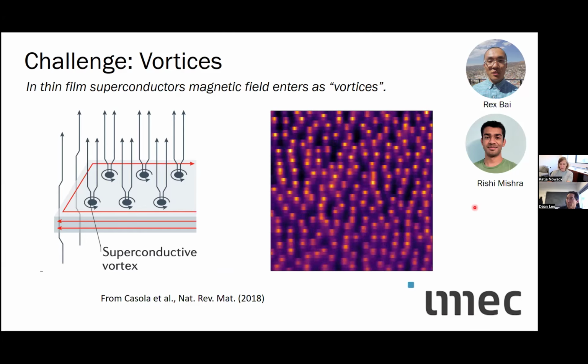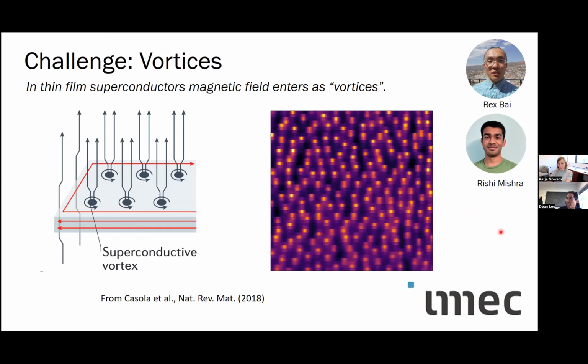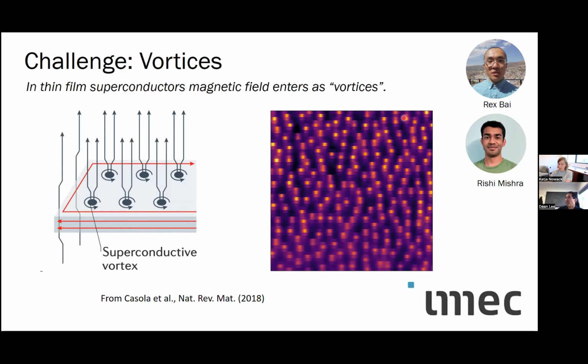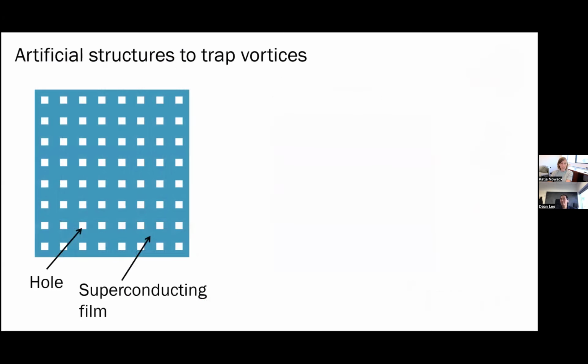And so they need to really understand and control where these vortices actually end up in the thin films. This is the kind of work that we can try to support. One way to control where the vortices are is to make artificial structures. If you punch an actual physical hole in the film and a vortex gets created, it's energetically beneficial for the vortex to hang out in that hole. There's some competition with defects in the natural film this is made from.